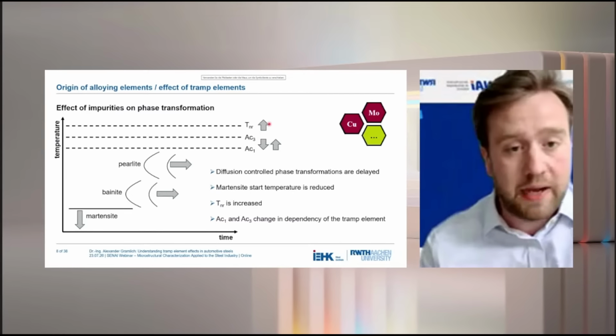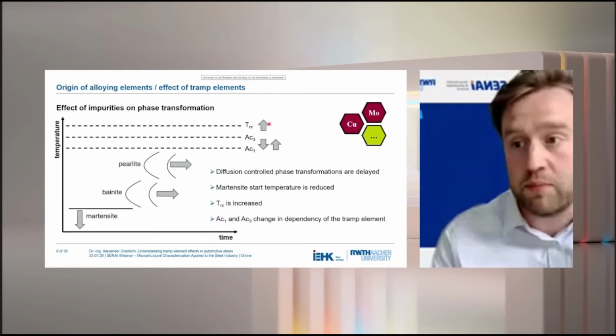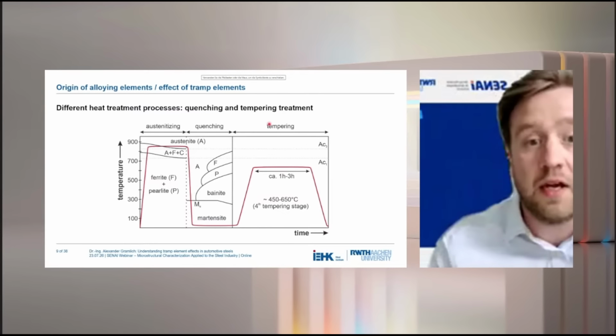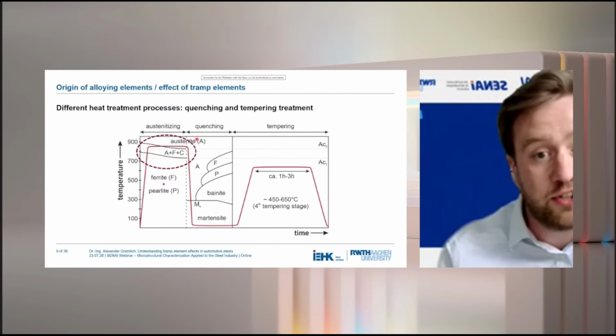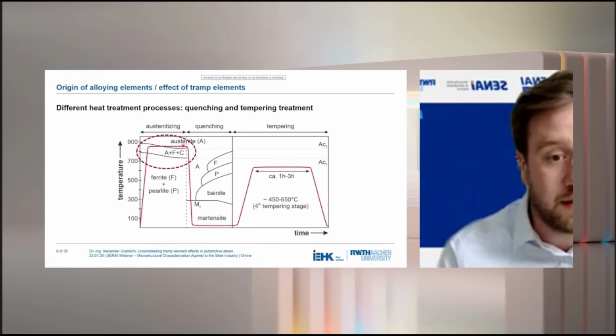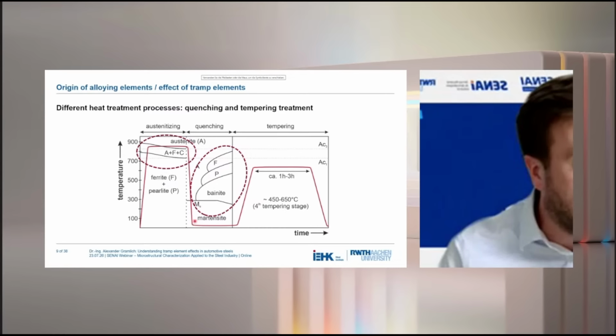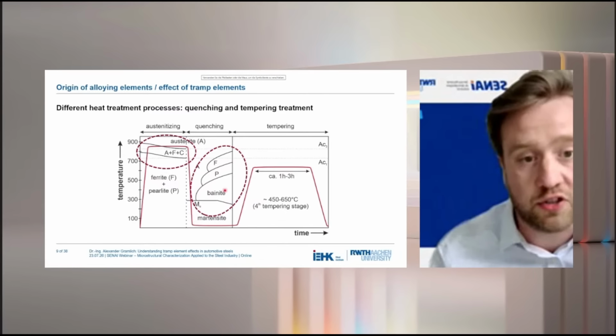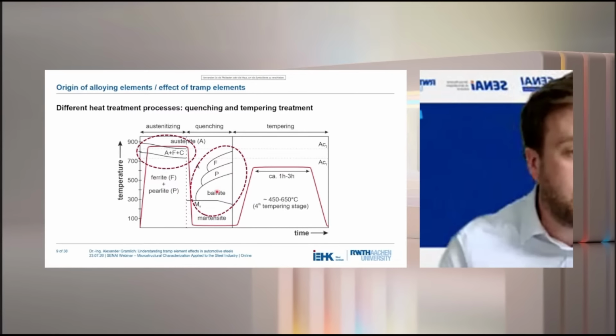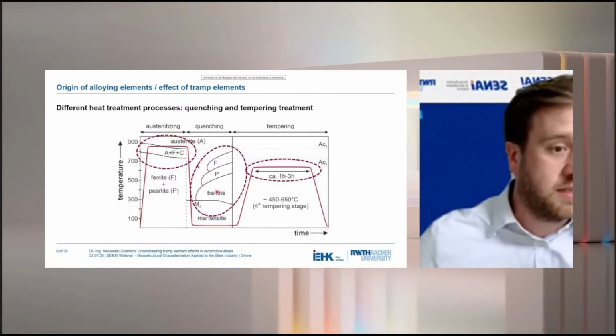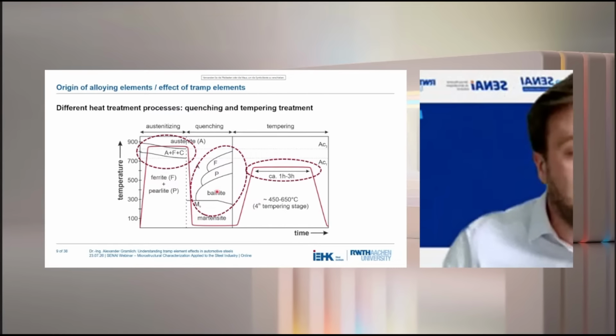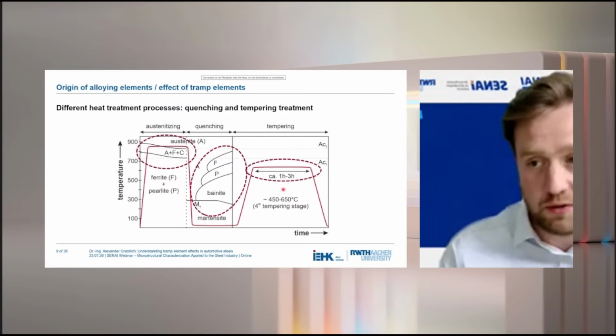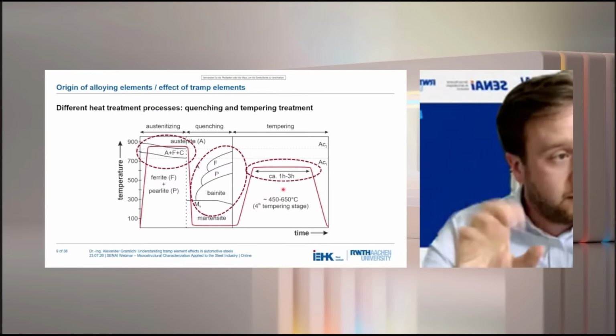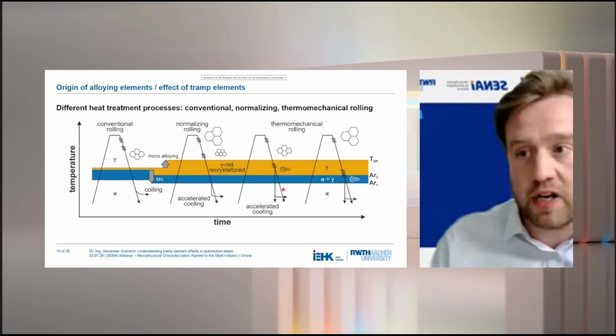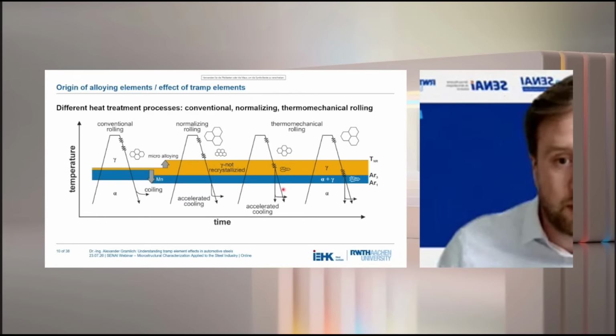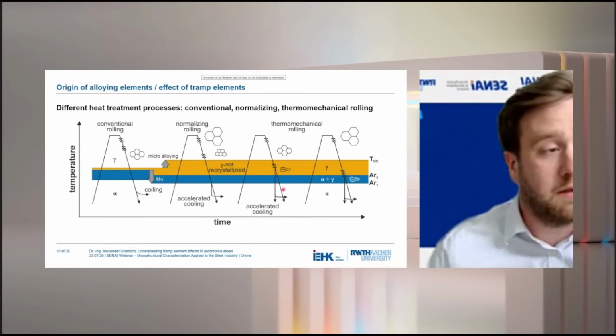And when we are looking now, based on these changes, for example, at a typical quench and tempering process, also schematically shown, we have influences on the austenitization temperature as A1, A3 are modified. We will have an influence on how fast we have to quench to achieve a fully martensitic microstructure, because all of these phase fields are modified by the tramp elements. And finally, we will also see an effect on the results we get after tempering, as carbide growth, for example, is also influenced by tramp elements. This is for classic quench and tempering steels, maybe a forging product, but also when we are talking about thermomechanical rolled products, we have to assess the effect of tramp elements.